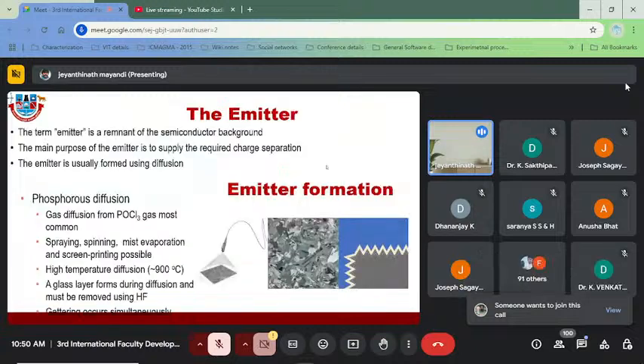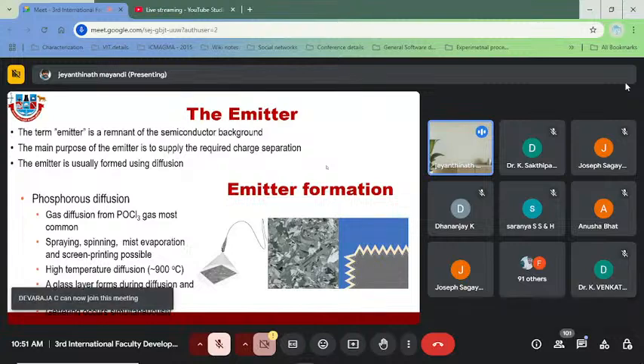And then you can make the emitter formation. Because the starting material is only p-type silicon, to make it an emitter or PN junction, you need to dope it with phosphorus, and this can be done by different methods. One of the methods you see in the video is POCl3, where phosphoryl chloride gas is passed over the wafer, which is heated in a high temperature tubular furnace in a controlled ambient at 900 degrees Celsius. A glass layer is also formed during the diffusion of phosphorus, and this glass layer is removed by HF etching.